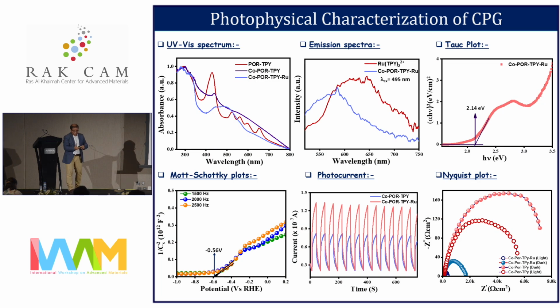So in this case, when we connected it, you can see the MLCT band, and this is from other characterizations we have done - this is the photocurrent and this is the impedance measurement. When you have cobalt, you can see the charge transfer resistance is much lower, and from the photocurrent it shows very fast, facile electron transfer.